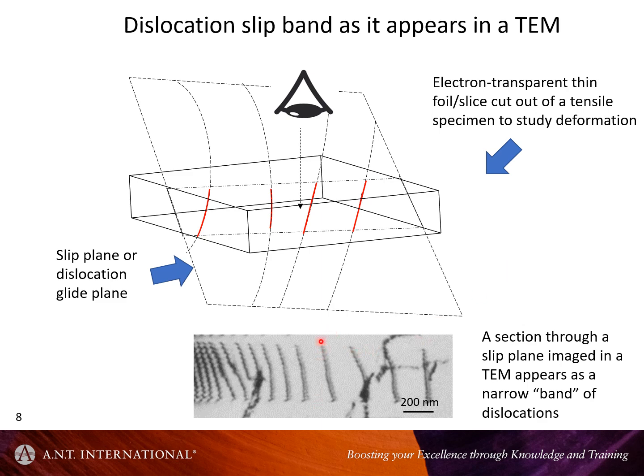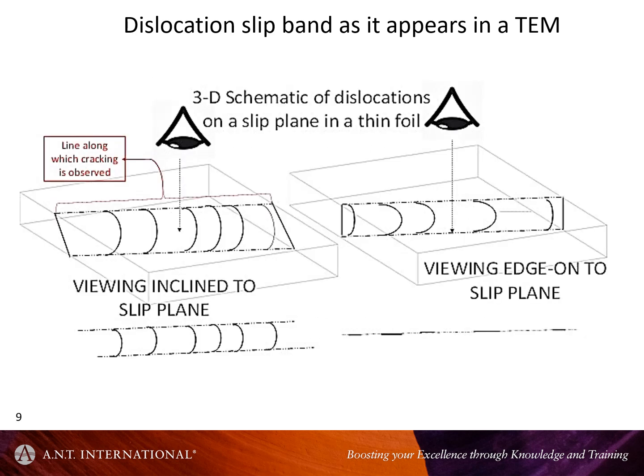The implication here, and I think this is where some people get mixed up, is that it appears like it has a finite width, but it really isn't. It's basically an artifact. If you think of it in those terms, it's human produced. It's an artifact of the preparation and how one images the material. So dislocation slip appears as a narrow channel in TEM because we're looking at a projection. And so channel, that's the right way to describe it.